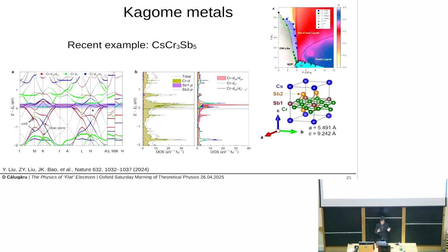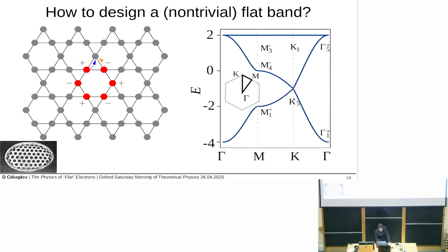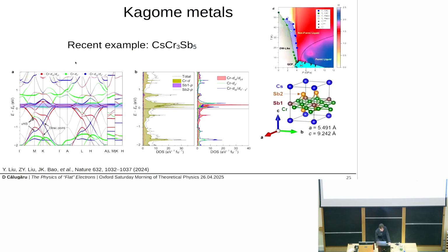And the band structure as a whole seems to have signatures of the Dirac band structure. So we had this Dirac cone here, we also have it here, we have the flat bands. Now what's especially interesting about this compound is what happens under pressure.